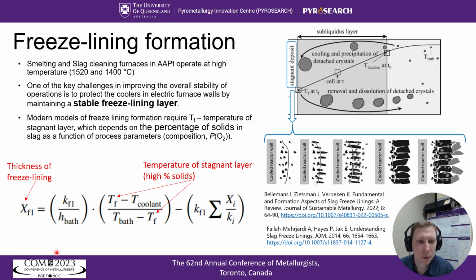We can see that the model requires an important parameter, the temperature of the stagnant layer where freeze lining is stable. In earlier studies, this temperature was often selected to be just the liquidus temperature, but later it was demonstrated that the temperature is between the liquidus and solidus. More accurate value for the freeze lining temperature can be obtained by better understanding of percent solids in the slag as a function of temperature. Let's demonstrate that it is not as simple as a half distance between liquidus and solidus, as was suggested by some authors.